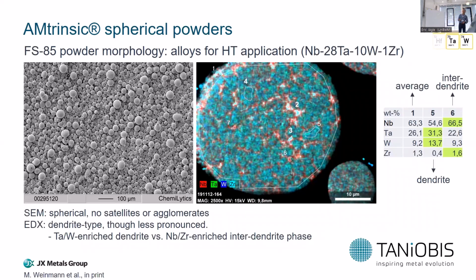A very similar finding is observed by investigating this FS-85. I mentioned this powder. This is a niobium-based alloy, because this has a very high potential and is a frequently requested alloy for application in satellite thrusters, for example. Again, the SEM shows nicely spherical particles, and the EDX shows a demixing into a dendrite phase, which is here shown in blue. And this dendrite phase is enriched in tantalum and tungsten, compared to the interdendrite phase. These are the white spots, which is enriched in niobium and zirconium.